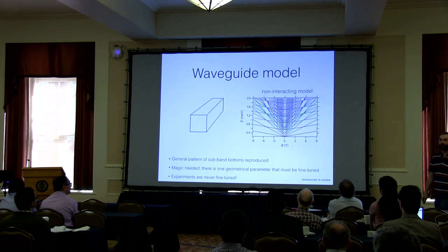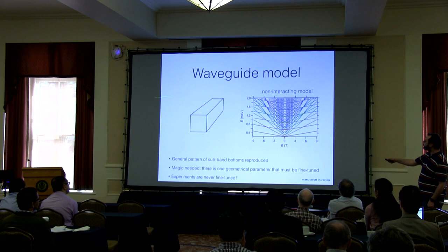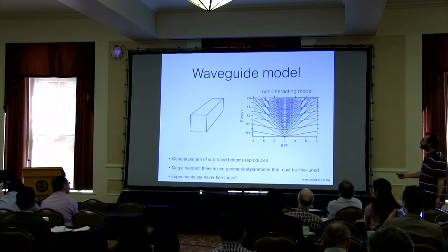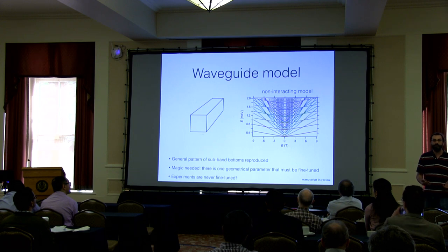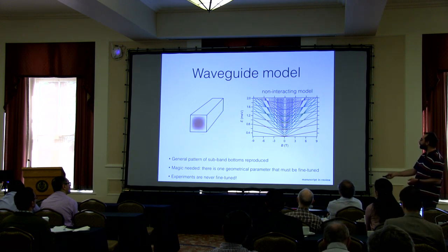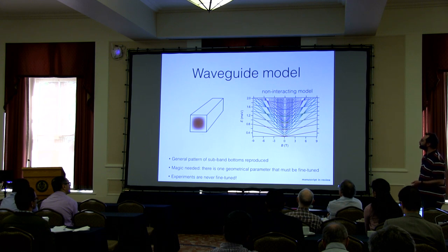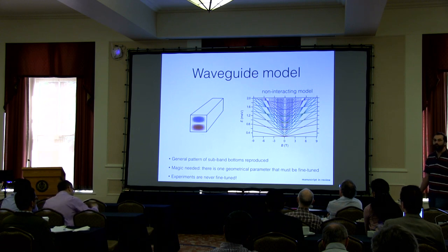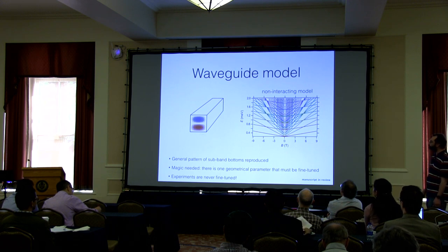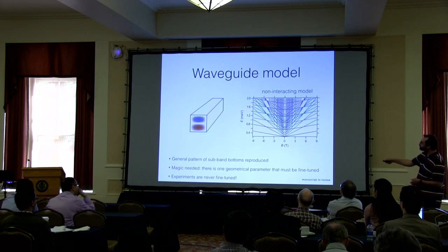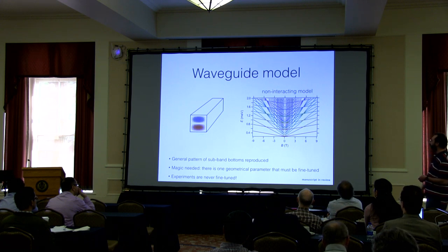Well, we have this waveguide model, which Jeremy started to introduce. We think that our ballistic nanowire is basically like a waveguide, but it's not a waveguide for photons, it's a waveguide for electrons. This waveguide, like any regular waveguide, has transverse modes in it. For example, here is a base mode, here is the first vertical mode, first horizontal mode, and so on. Now, the idea is the pattern of the crossings of the subbands is the result of the modes of the waveguide. So by tuning the magnetic field, we tune the energies of these modes, and we can make them come together at certain points, and this results in the Pascal sequence of crossings.